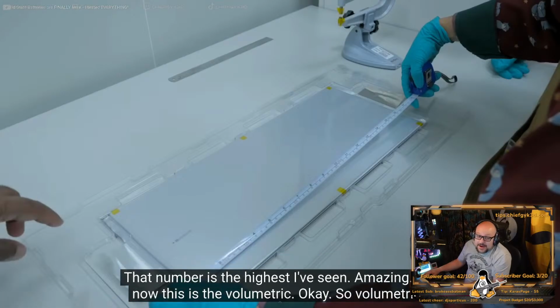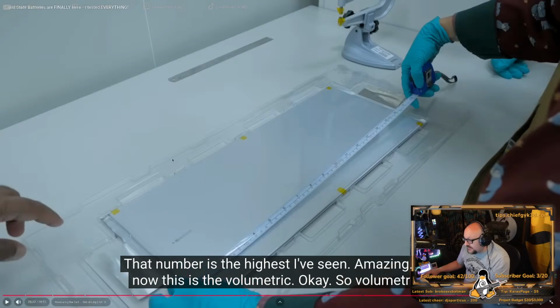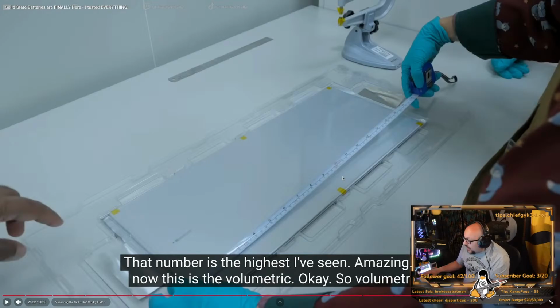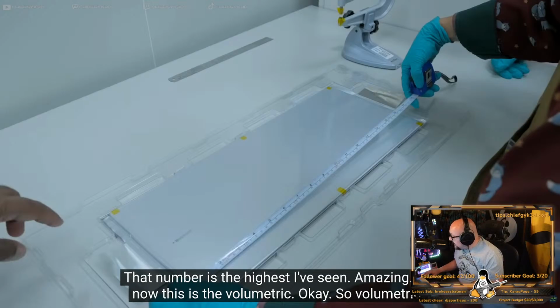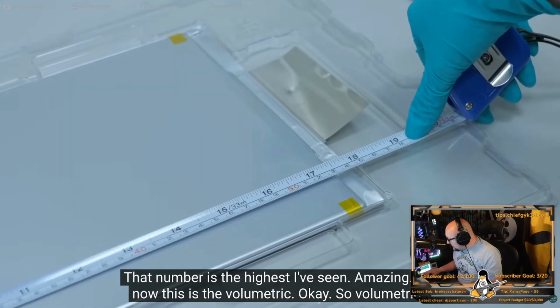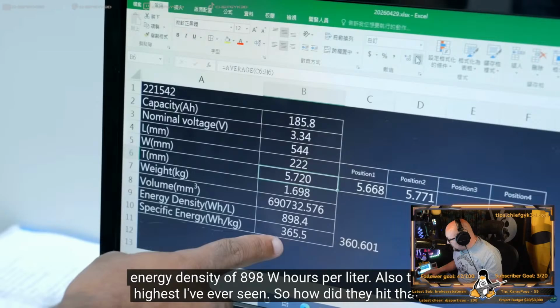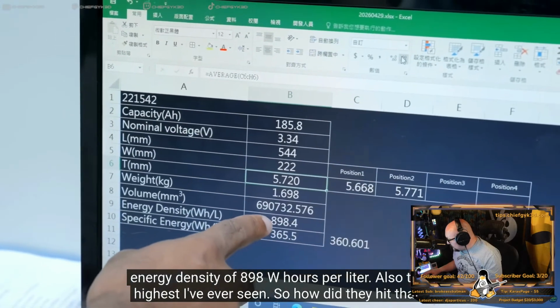Amazing. That's what I was blown away by, because let me see. Lithium ion watt hour density is 150 to 350 watt hours per kilogram by weight. So this is kilo for kilo on par with the best lithium ions. This is looking like this should be the replacement for lithium ion battery technologies. So now this is the volumetric. Okay, so volumetric energy density of 898 watt hours per liter. Also the highest I've ever seen.